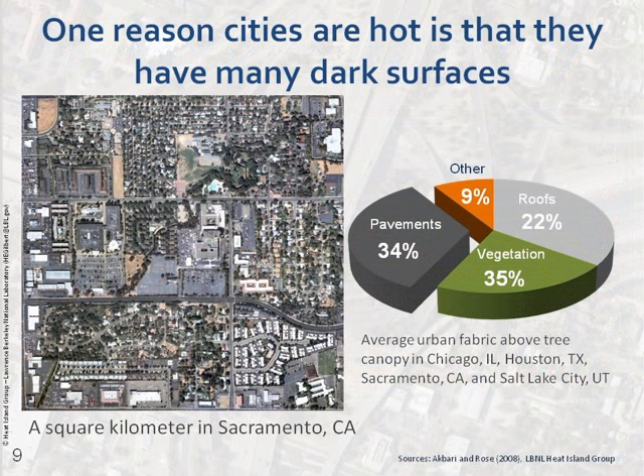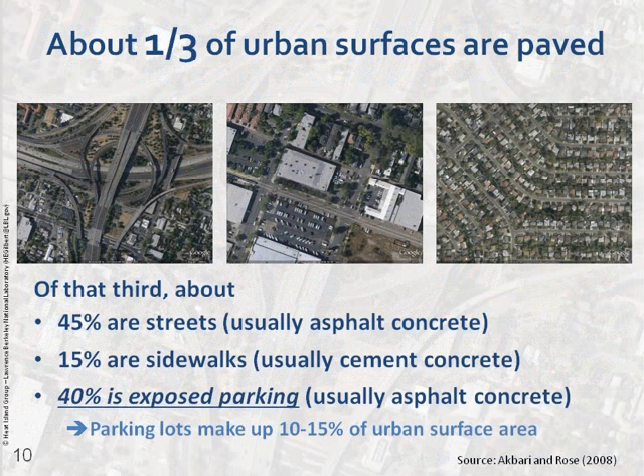Pavements are traditionally dark and made of black asphalt. So about a third of U.S. cities are pavements, and of that third, we normally think of something like streets as being the largest chunk, but in fact they're only 45%. Another 15% is made up by sidewalks, which are usually lighter in color because they're made from cement concrete traditionally. But another 40%, and importantly for this meeting, 40% is exposed parking lots, which are traditionally made from asphalt concrete. So 40% of about one-third means that exposed parking lots can actually constitute 10 to 15% of a city's total surface area, which is a big chunk.